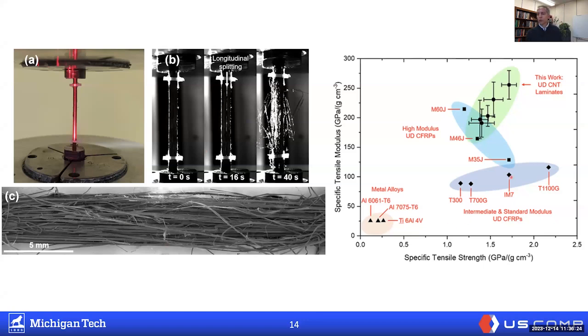And this graph is very similar to what I showed a few minutes ago, but this is specific to the paper for the results of this paper. And what you can see here is the standard deviation of the different laminates that were fabricated as part of this individual effort and where they stand on this property graph. By the way, each of these data points represents a different matrix resin. So I believe this top one was a benzoxazine. We've got a bismaleimide. We've got some cyanate esters in there. There's more details in the paper. But by being able to use these types of carbon nanotube yarns, different resins, we're able to show very nicely that this type of composite works really well for dramatically increasing the modulus over state-of-the-art composites.